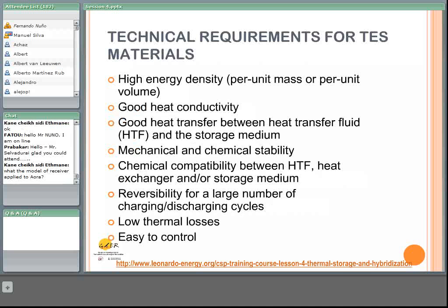It's also desirable to have good heat transfer between the heat transfer fluid of the solar field and the storage medium. Of course, the storage medium should be mechanically and chemically stable, and there should be chemical compatibility between the heat transfer fluid of the solar field and the storage medium. Normally, the heat transfer between these two fluids takes place at a heat exchanger, and we must be sure that there are no problems in these heat exchangers in the case of a leak or any other incidents. It's important to ensure safety in all cases.